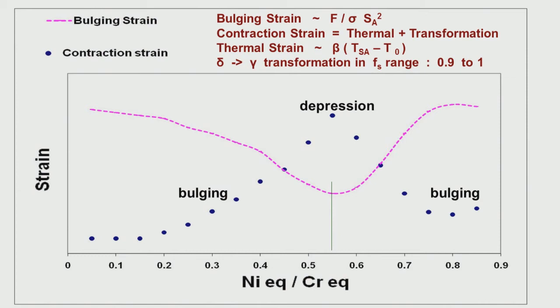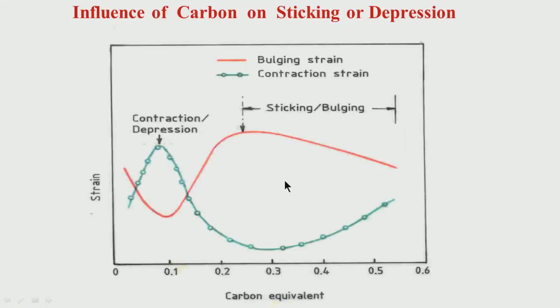The same thing has been explained pictorially. For stainless steels, around 0.55 you have relatively high contraction strain, so you have depression, and the bulging strain is relatively less. For very low nickel equivalent by chromium equivalent, the reverse is true, you have bulging, sticking, and for high nickel equivalent by chromium equivalent, that is the AISI 310 type of grade, we again have bulging. A similar effect for carbon grades: you see, around 0.1 the contraction strain is relatively high, so we have depression tendency, and for very low carbon or very high carbon, you have sticking and bulging tendency.